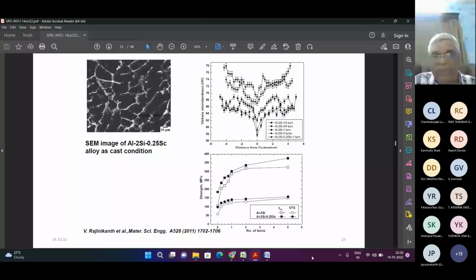By using the ball indentation technique on all these samples, with 10 mm diameter and 1 mm thickness reduced to 0.8 mm thickness, you can see that the strength has increased up to 400 MPa. This is for aluminum 2 silicon 0.25% scandium. We published this paper with my colleague V. Rajnikant at NML Jamshedpur, and we have given the reference at the bottom.